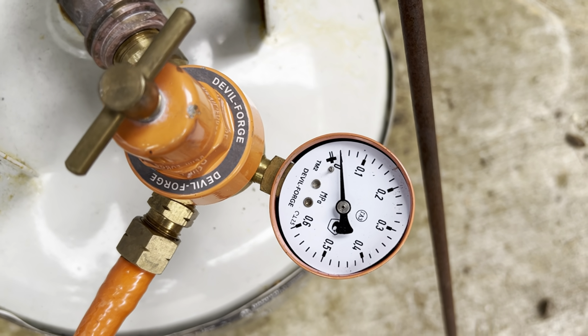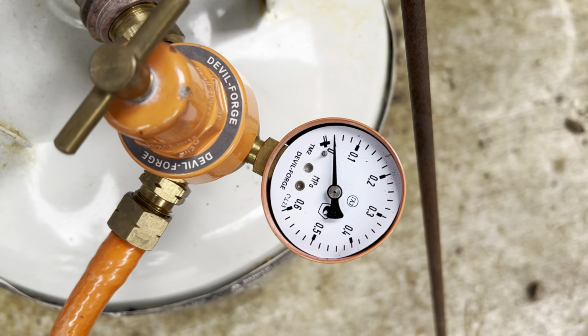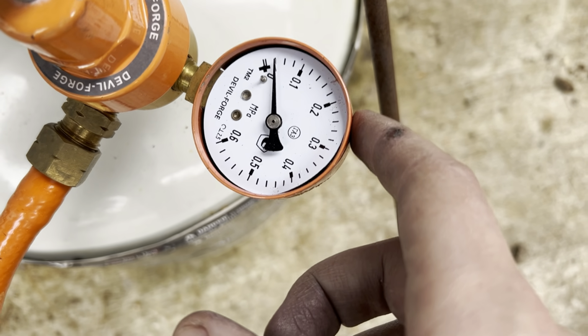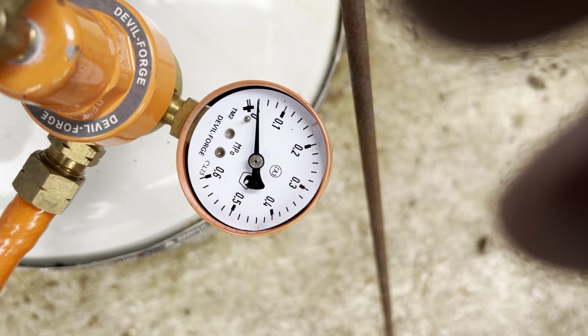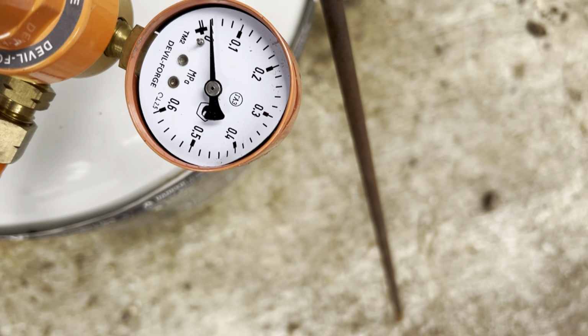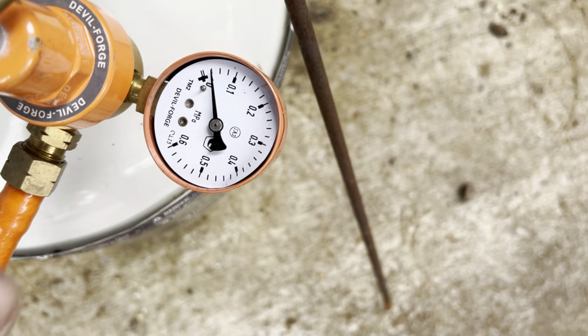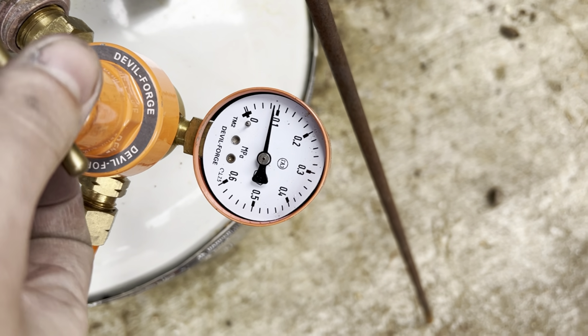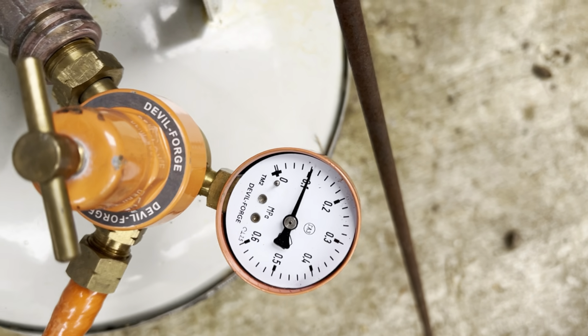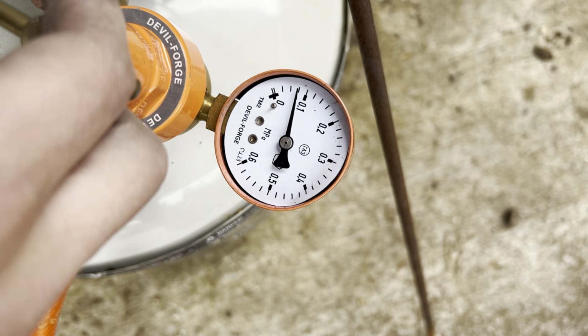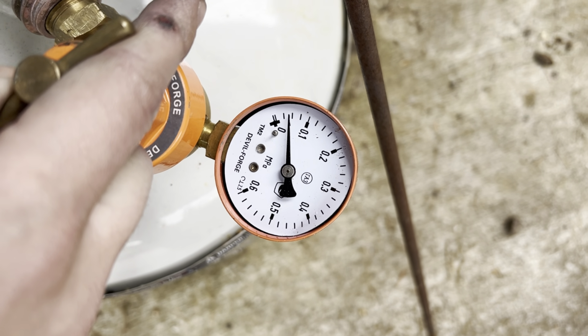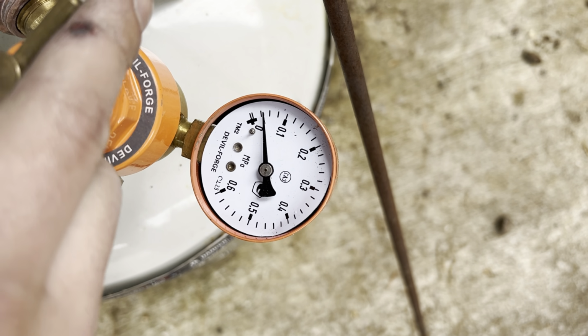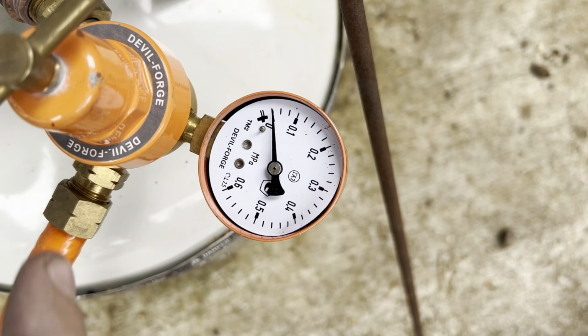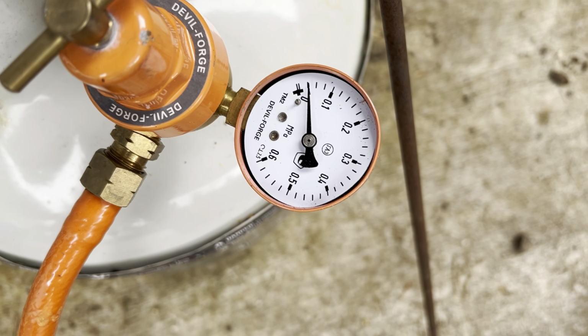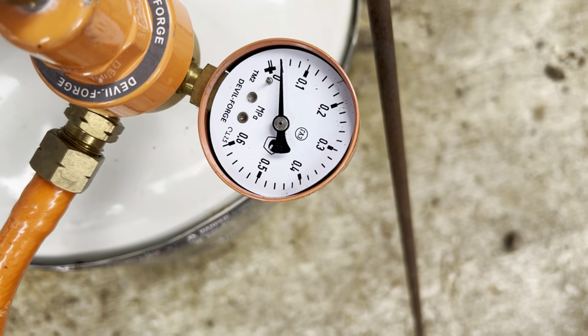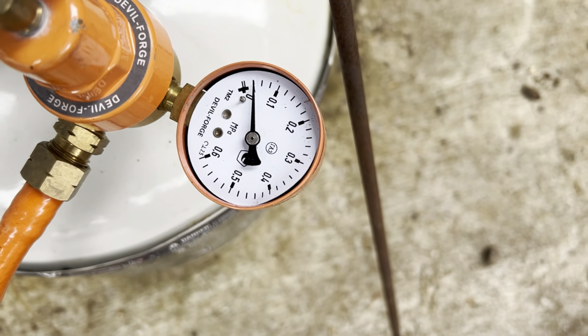When I'm melting brass, I like to keep the flame down pretty low. So I usually don't ever go above that 0.05 MPa mark. Any more than that and the brass can start to overheat. So like this is way too much, way too hot. It'll waste gas. It might take a tiny bit longer to heat it up slowly, but heating it up slowly ensures that your brass isn't going to get overheated, and it will result in a much cleaner and overall just nicer melting experience.